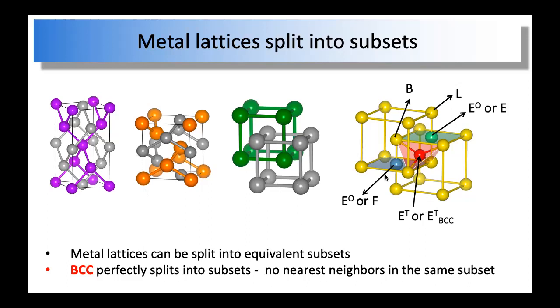Another very important thing is the high symmetry positions of the two subsets. They have particular relations. For example, a face center of one subset is the edge center of another subset, right? Another important point is the body center of one subset is the atomic position of another subset, right? And also a very important feature is the midpoint between the edge center and the face center. This point is the same for both sublattices. That means if it is a midpoint for one sublattice, it's also the midpoint of the other sublattice, right? So this is the very important geometric feature of the BCC lattice.